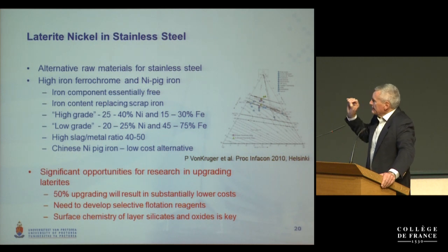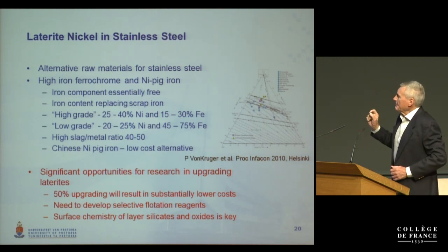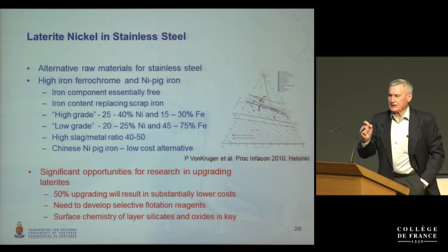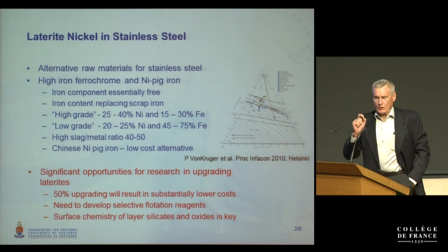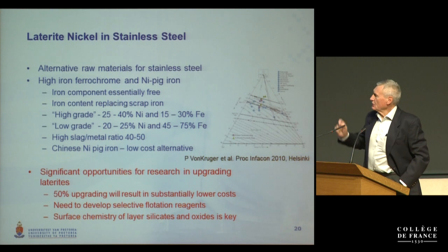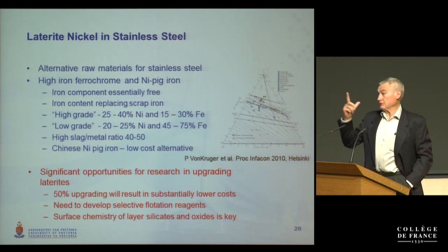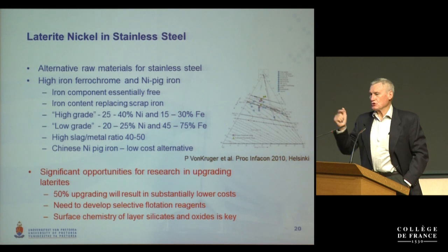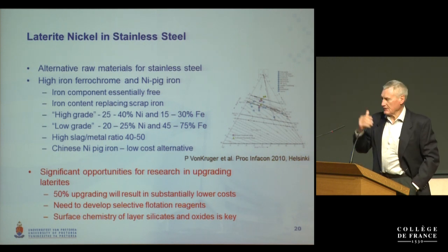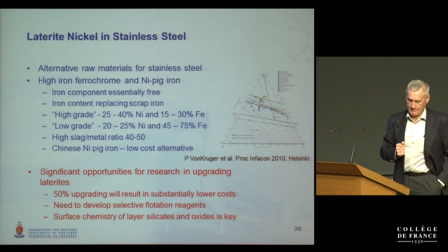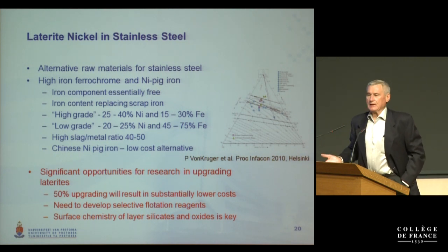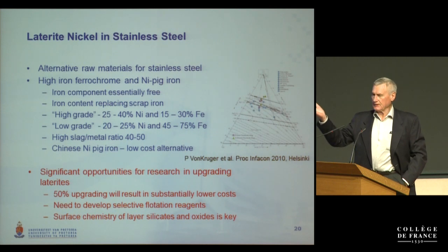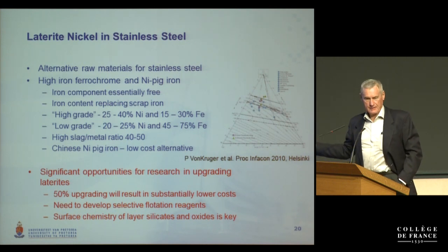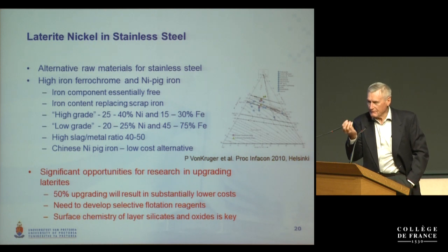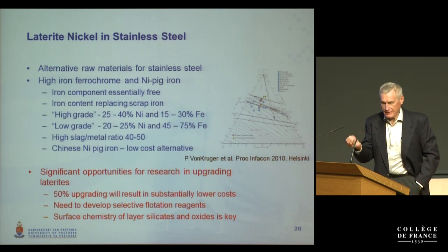So there are two grades that are produced, but the main problem is the slag to metal ratio. You expend a lot of electrical energy to heat up 98% of your material to get 2% metal, nickel metal. Let's say 5% nickel metal. So therefore, you spend a lot of energy heating up the material, cooling it down, and throwing it away to be able to recover this 2% nickel product.